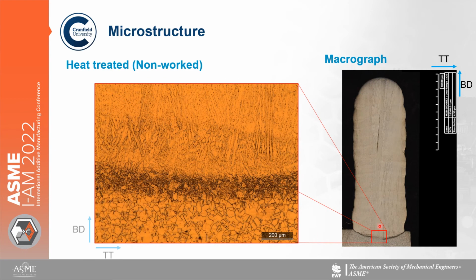And if we look at the very bottom of our sample, where the Rene 41 interfaces with our Inconel 718 substrate, you can see the wrought 718 on the bottom for our substrate plate, and where it interfaces with the Rene 41. You can also see a remelt line here, which is where the material has been remelted as we deposited the next layer. And again, you can see our dendrites as well, orientated in the build direction.